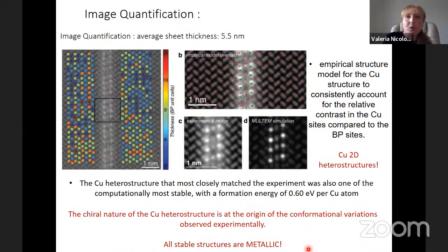What we also understood by doing some image quantification with our colleagues in Antwerp was that if we built the structure through our CVD and our DFT calculations, and then did the experimental imaging and the image simulation, the matching structure was not a 2D wire, a 1D wire really, but a 2D wall basically. We had a heterostructure growing across the thickness of the whole 2D material, if you wish.